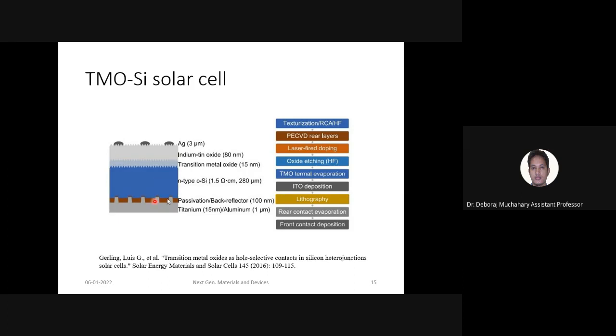And after that, what they have done is thermal evaporation of the TMO. These transition metal oxides, they have thermally evaporated them. The thermal evaporation technique they have used to deposit these thin layers of about 15 nanometers of transition metal oxides. Then on top of this they have used one indium tin oxide, or ITO, layer. The ITO layer is a conducting oxide, very highly transparent but highly conductive also. On top of this they have used silver electrodes, 3 micrometer, and on the back side they have used titanium aluminum metal contacts. So this is the complete picture of a TMO silicon solar cell, and these are the process steps.